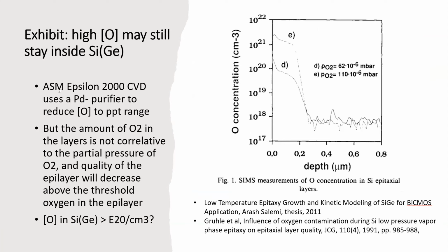It has that, it's an ASM Epsilon, this old tool. The new tool is the same. They have the palladium purifier that will capture the oxygen to the PPT level. Pretty good. That's parts per trillion. It's a very nice number. But sometimes you still need to watch out that your oxygen concentration in your epi, in a silicon epitaxial layer, could go as high as 10 to the 20, 10 to the 21 per cubic centimeter. This is pretty high. This is like 1% of the atomic density, and that is not good, right? So oxygen higher than this will give you device problems.